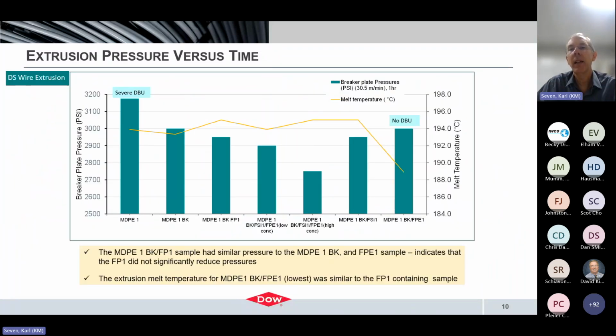Okay. So here, what we did was we took selected examples or samples of these medium density jacketing compounds, and we evaluated those in a full-scale wire extrusion coating line. Here I'll point out a few things. I show breaker plate pressure, melt temperature. So basically, these results are showing the typical fluoropolymer had similar pressures to the control sample or comparative sample MDPE BK. That's the sample without processing aid, and also similar to the polar polymer additive sample. These results basically indicate that the fluoropolymer did not significantly reduce pressures overall, but neither did the polar polymer additive.